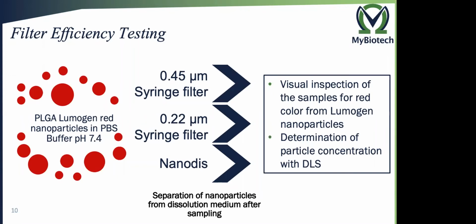Another good thing about these particles is you can really see by visual inspection if the nanoparticle filtration is efficient or not, because the color of these particles is pink. If you don't have any particles in the medium, it is transparent, colorless. If you have nanoparticles in the medium, you will see a pink color. What we did is three different filtrations with these particles: through a 0.45 micrometer syringe filter, a 0.22 micrometer syringe filter, and we used our Nanodis system.